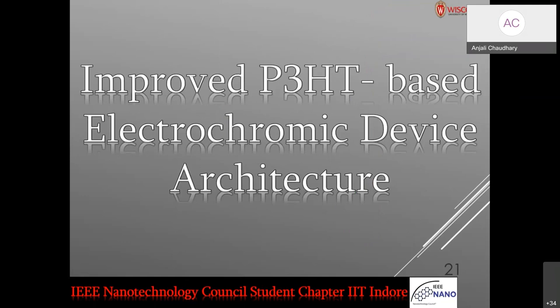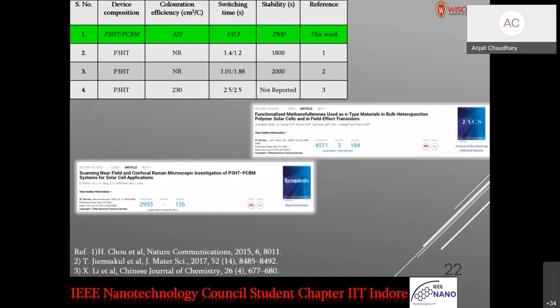So how can we improve this P3HT based device performance, because it shows a color switching time of 4 seconds and nearly 2 seconds. So we combine it with PCBM, which is again an organic molecule, and we see that it shows very good properties with a coloration efficiency of 321, a switching time of a second, and 2500 seconds of stability.